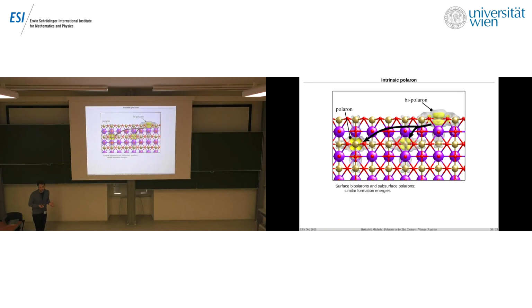This is actually a bipolaron. So it takes half electron from 4 unit cells. So there are 2 excess electrons. They come together and they localize on this site. And I would say this is kind of a genuine small electron bipolaron because it doesn't involve any dimerization of surrounding atoms. This is actually the same as a small polaron, a small single polaron, where you have one electronic charge localizing there, deforming a bit the lattice bond, but the difference is that you have 2 electrons.